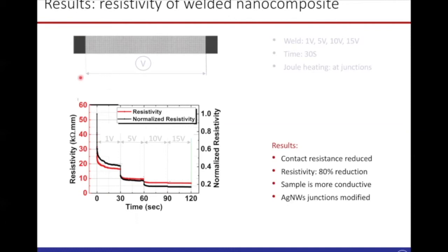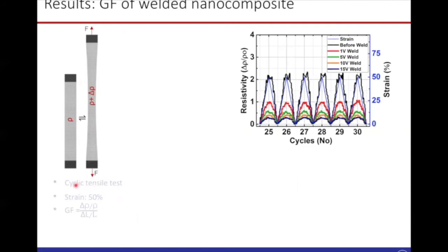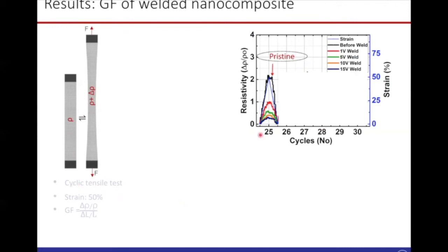Now this sample is without applying a strain. Now we want to check how the welding could affect the gauge factor of this sample. So here we show a tensile test and the change in gauge factor by applying 50% strain on this sample. And we apply this strain cyclically for 30 cycles. Here is the result of this test, change in gauge factor with respect to the welding. The left y-axis shows the change in resistivity and the right y-axis shows the strain.